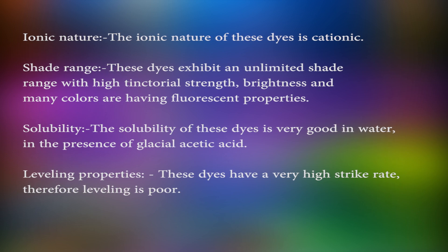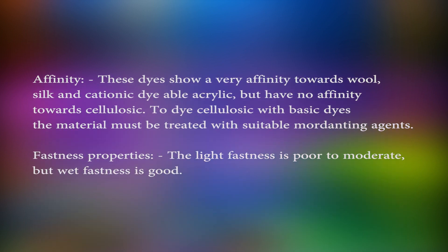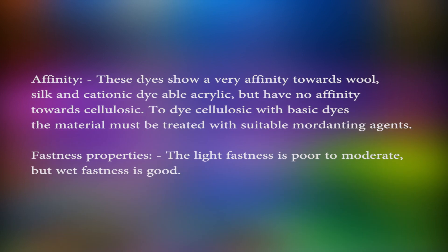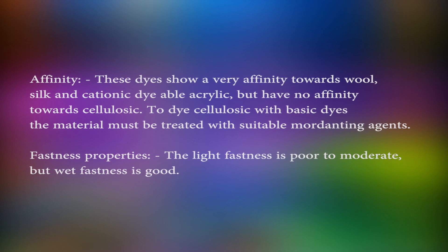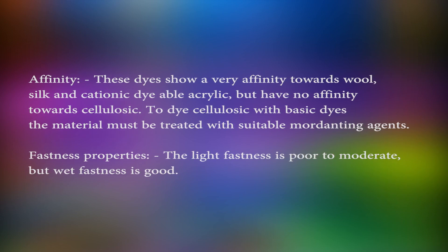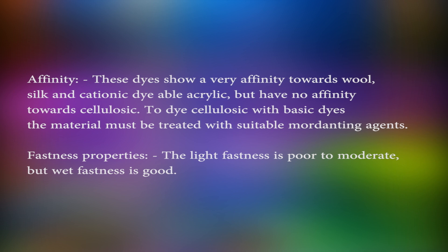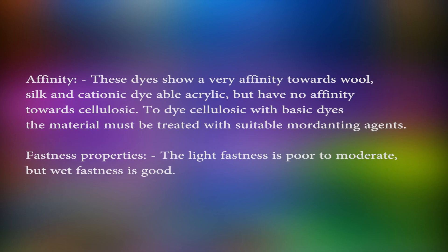Leveling properties: these dyes have a very high strike rate, therefore leveling is poor. Affinity: these dyes show very high affinity towards wool, silk, and cationic dyeable acrylic, but have no affinity towards cellulosics. To dye cellulosics with basic dyes, the material must be treated with suitable mordanting agents.